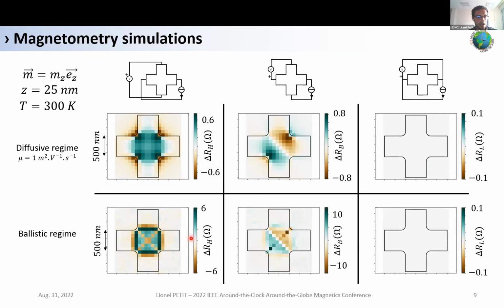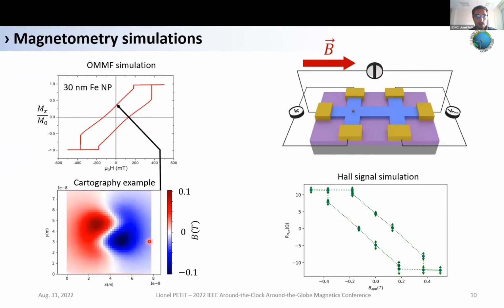So now we have this in mind. We can choose an area with high sensitivity, for example, and instead of placing a standard dipole, we can simulate with a true nano object, such as a 30 nanometer iron nanoparticle. So we simulated that. It's magnetized along the x-axis with a magnetic field along the x-axis too. So we did that on OOMMF, and from that we can extract a cartography that we plugged into our ballistic model.